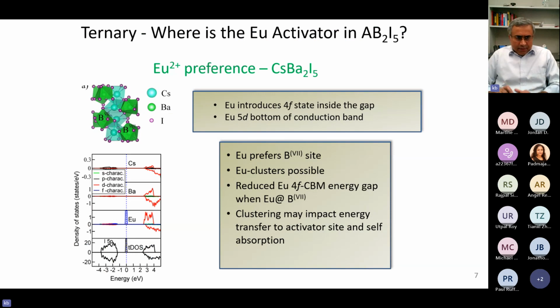So like I said, we always start with the structure of the host crystal. In this case, it's cesium barium iodide. It's a complex structure. It's a monoclinic structure, which of course, from a crystal grower point of view, is not easy to grow compared to, let's say, nice cubic structures. In any case, sometimes the difficulty in growing can outweigh the beneficial properties in terms of scintillation that they might have. So it's always a balancing process. There is always some trade-off involved.